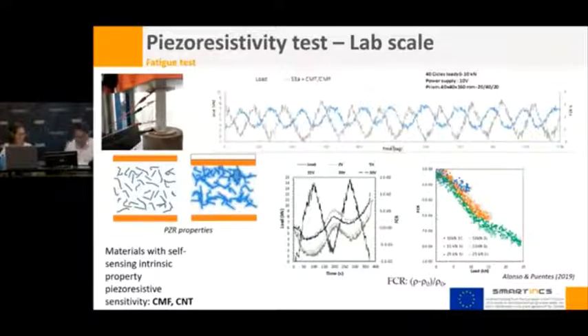Once the basic parameters and the type of result obtained were identified, the objective of the test was focused on the fatigue of the material. It was the next stage, comparing the values as a function of the applied load. With the fatigue test, a hysteresis phenomenon was observed, identified in the literature as polarization. A constant increase of the fractional change in resistivity value along the test is due to exposure to the electrical field, depending on the microstructure of the material. This factor was neutralized by applying the current without change until the sample reached equilibrium. The resistance time was 30 minutes.